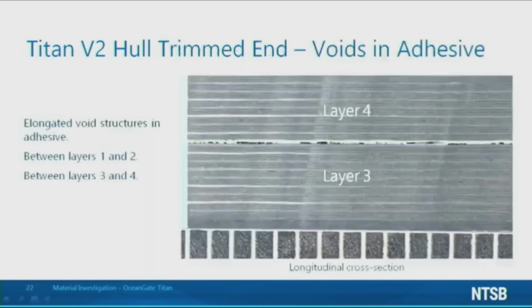Finally, investigators observed voids in the adhesive used to join the co-bonded layers. Some voids were present in all layers. However, at the interface between the first and second layers and between the third and fourth layers, some of the voids formed elongated structures in the adhesive. These structures were visible on longitudinal cross-sections like the one shown.